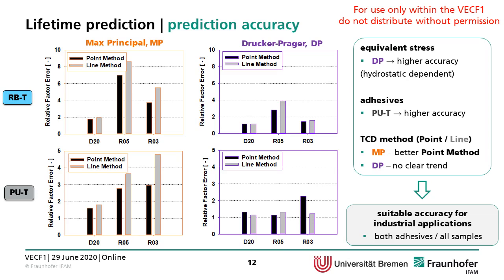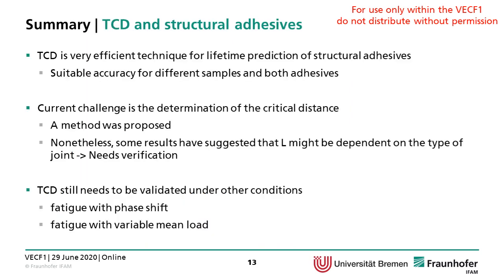But it's important to highlight that by using the Drucker Prager equivalent stress, we had a suitable accuracy for industrial applications, which for adhesives, it's around 5 to 8. A factor of 5 to 8 is good. And this was obtained for both adhesives and all types of samples.